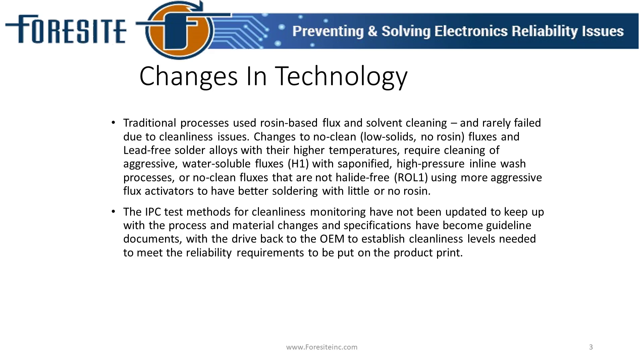The reality behind those no-clean flux residues meant that you had to have good clean hardware coming in, good clean boards, good clean components, and fully heat-activate the flux so that it was benign. Since 1991 — we started our company in 1992 — we found that there are a lot of dirty incoming boards, dirty components, and dirty flux application issues that have created a huge shift in reliability issues.